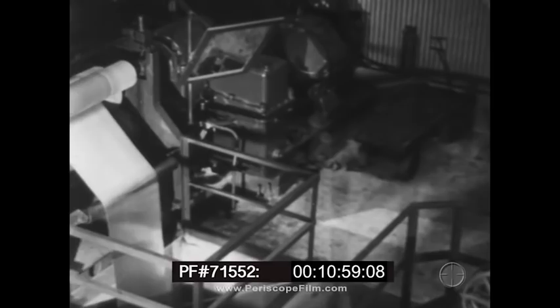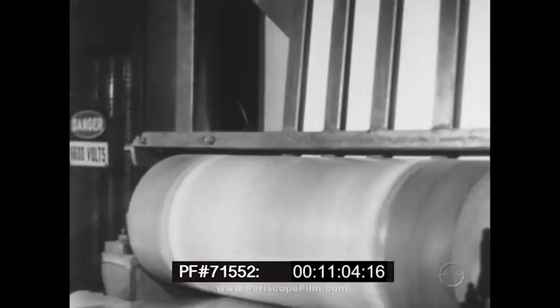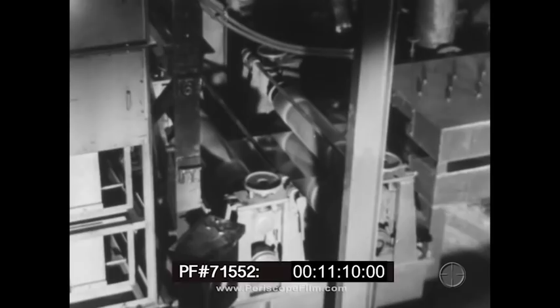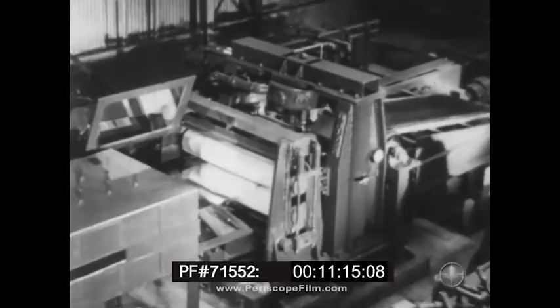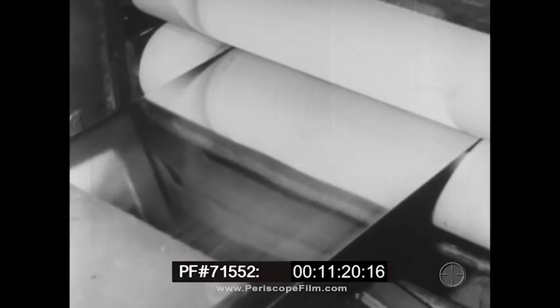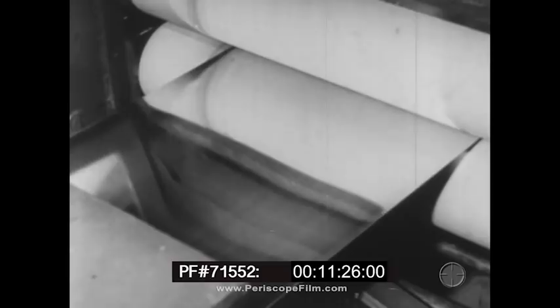Next comes a vital step. The strip is raised to the top of the heater unit housing, inside of which is a series of high-frequency coils. As the strip comes down through these coils, induced electric current causes heat, which flows the tin almost instantaneously, greatly improving its structure as a protective covering. Here's the result. Tin plate that is mirror smooth, free from porosity, so perfect a protective covering that 1 pound of tin can now do the work of three.